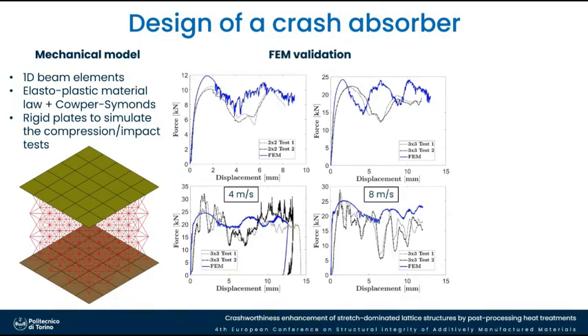In the two figures on the top here, you see the comparison for the 2x2 and 3x3 specimens. Then for the strain rate dependency, what we did was we calibrate the model on one velocity, 4 meters per second, and then we checked that all the results were in agreement also on the other velocity. And so the agreement between the finite element model and the experimental results validated our model.